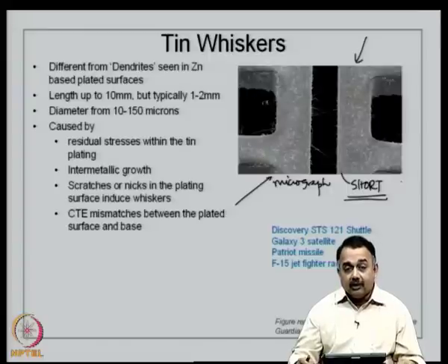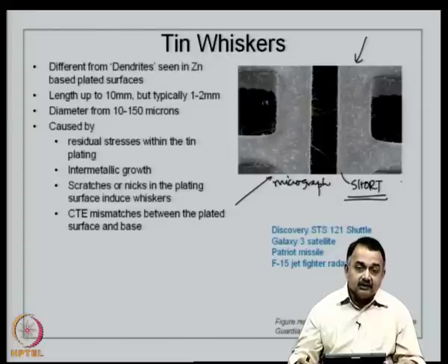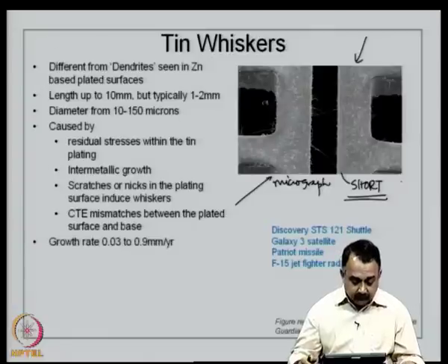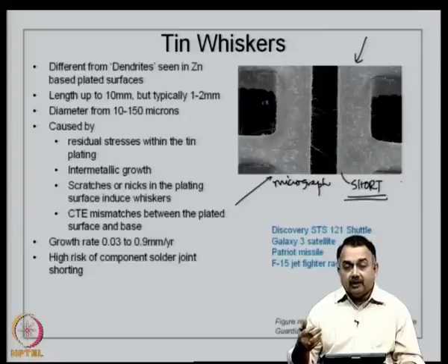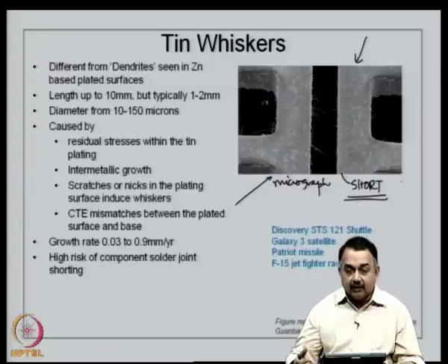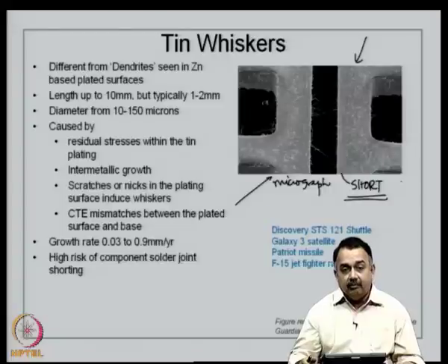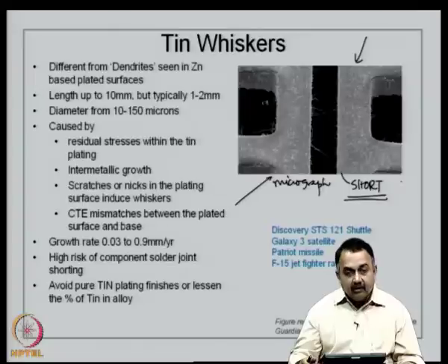And this is also caused by CTE mismatch, that is coefficient of thermal expansion mismatch between the plated surface and the base. So, the growth rate is 0.03 to 0.9 mm per year, that is almost 1 mm per year, and typically not observed immediately, but during the working of the product, one fine day you find a defect in the product, and if you troubleshoot and see it is a tin plated board, you can definitely expect tin whiskers. So, it has a high risk of component solder joint shorting, and the best thing is to avoid pure tin plating at all cost, or lessen the percentage of tin in that alloy.